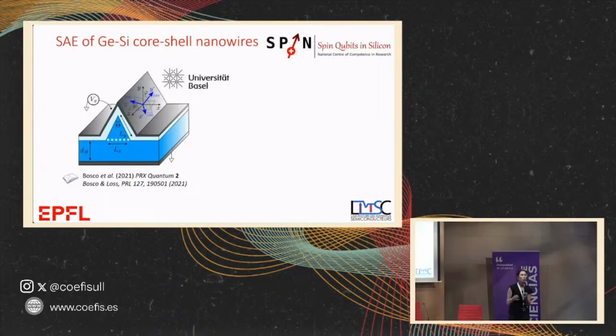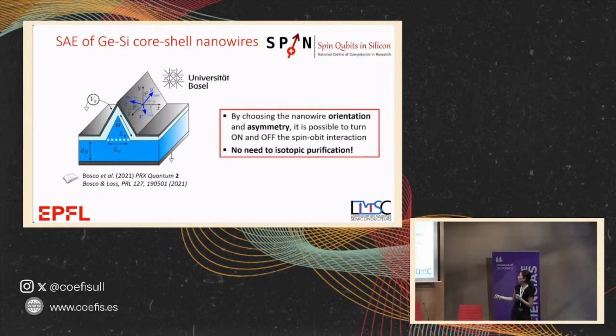So why do we want to have these standing nanowires? There's an additional reason for that. We can grow our germanium nanowires in selective area, but we can also engineer the shape. And the shape has an additional advantage. In fact, by choosing the crystal structure, the shape, and what kind of directions we're using, we choose the crystal asymmetry. And this allows us to play with this spin-orbit interaction that I told you before.